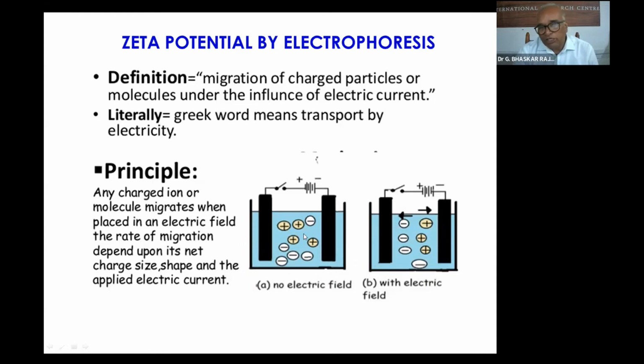Electrolyte means you should have a conducting solvent. It can be sodium sulfate or sodium chloride, some conductive solvent, or in water you put a simple salt like table salt, sodium chloride, or sodium sulfate. Then it becomes conductive. In that conductive medium, any positively or negatively charged material you put in gets into this state. The moment you apply power between the electrodes, the negatively charged things will come to one surface, and the positively charged things will move to the other electrode.